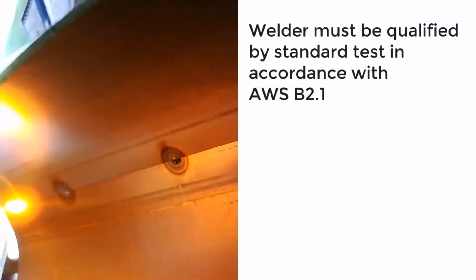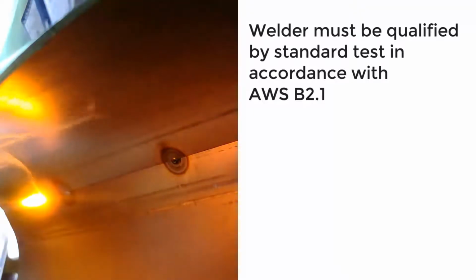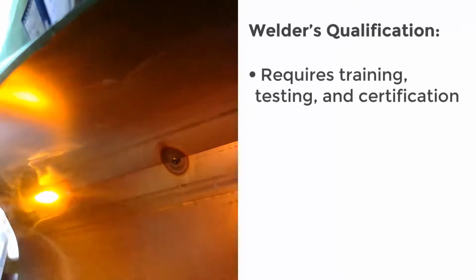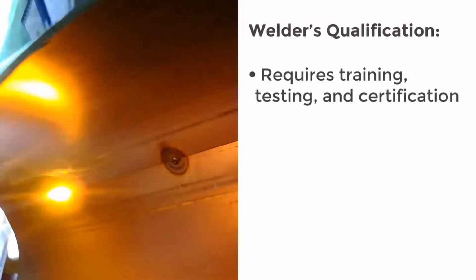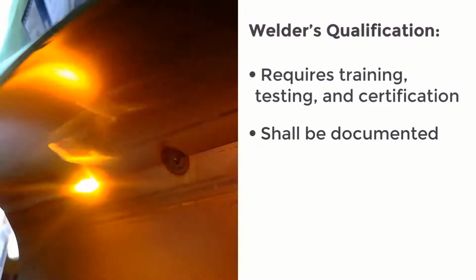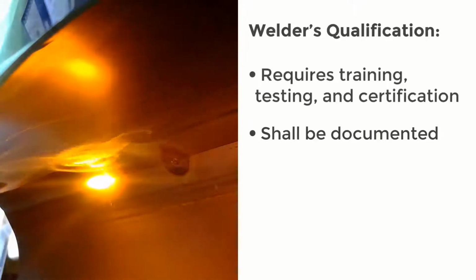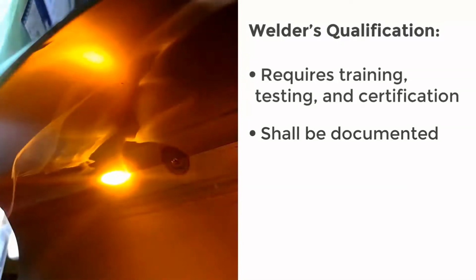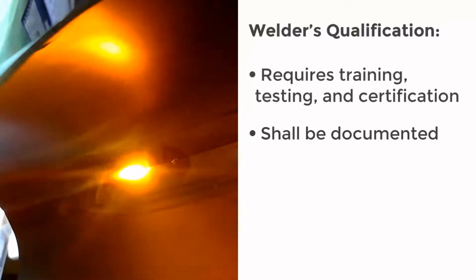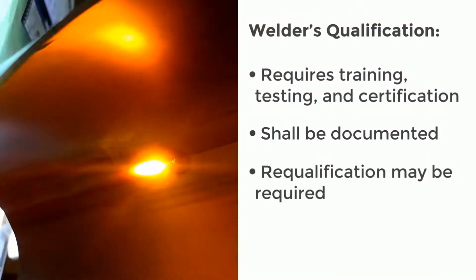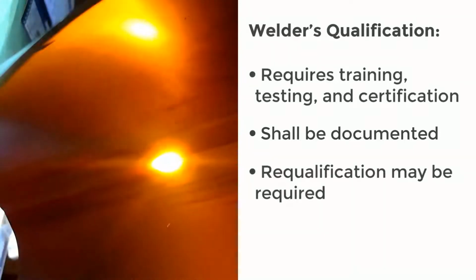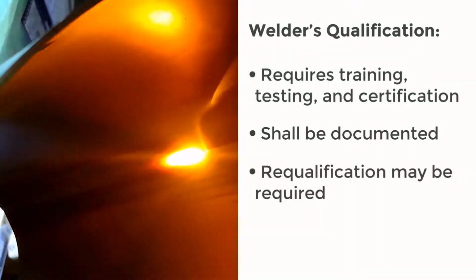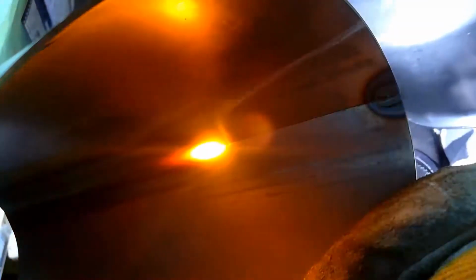To be able to produce a hygienic weld, a welder or welding operator must be qualified by standard test in accordance with AWS B2.1. In the United States, welder or welding operator qualification is achieved primarily by training, testing, and certification by the fabricator. The performance qualification shall be documented in any convenient format, provided all the test results and welding variables are recorded. A welder or welding operator must requalify when he or she has not welded with a specific process for a period of 6 months or more, or when there is specific reason to question the ability of an individual to produce welds meeting the requirements of AWS D18.